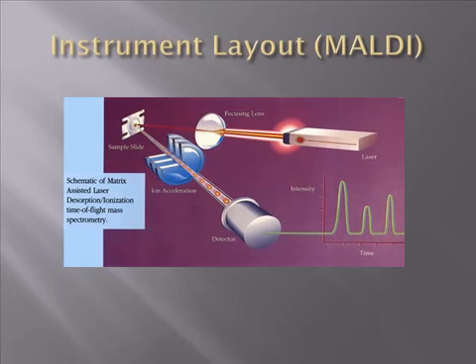A laser shoots short pulses of light at a 330 to 360 nanometer range, causing the sample to almost explode. This vaporizes the matrix and ionizes the sample into the plus one or minus one state. Normally the polymers are too big and heavy to evaporate, but at high temperatures and low pressures, evaporation occurs. This leaves us with ionized polymers in the gaseous phase.